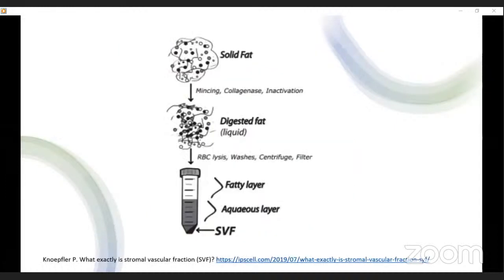Then, first of all, we divide the extracted adipose tissue into very small pieces. Secondly, we put in the collagenase because it destroys the extracellular matrix and exposes the cells. And at the end of the 1 hour, we first centrifuge the suspension obtained. And lastly, we pass it through micrometer filters. Then the SVF is ready.